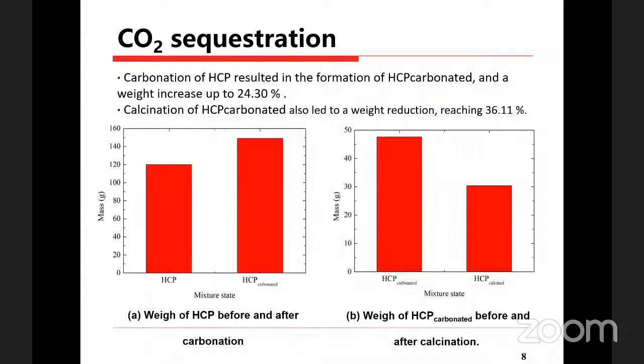That is CO2 sequestration, and here are some very initial results. We find that the carbonation of the hydrated concrete powders resulted in the formation of carbonate. We call this HCP carbonated, and we found a weight increase of up to 24%. The calcination of the hydrated concrete powders also led to weight reduction, as expected, and the weight reduction is around 36%.